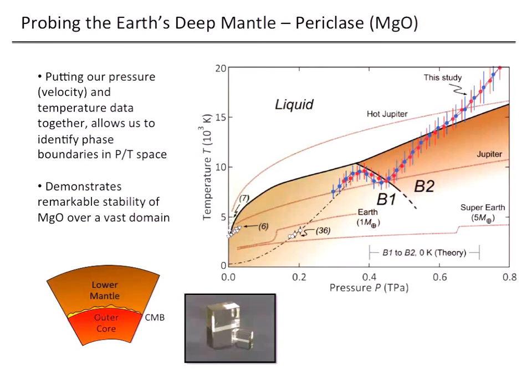The previous gas gun data were down here, but you can see that MgO is an extremely refractory material. The melting curve is likely very high, especially at core mantle boundary pressures, which are down here. So we're favoring the highest interpretations for the melting curves in that previous phase diagram that I showed you.